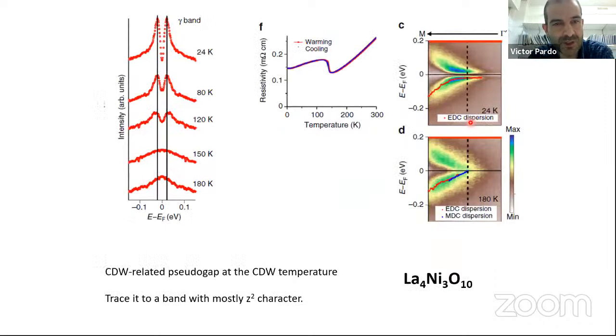Something else that we saw was that some of these nickelates have charge density wave transitions. You can see it here in the resistivity of this material, that it has this kink at 100 and something Kelvin, and you can trace it to the behavior of certain bands. You open these gaps. You have this typical charge density wave transition associated to opening of gaps at certain K points of the Fermi surface and related to certain bands. And what we could see by comparing ARPES and DFT calculations is that this is related to these z-squared bands.